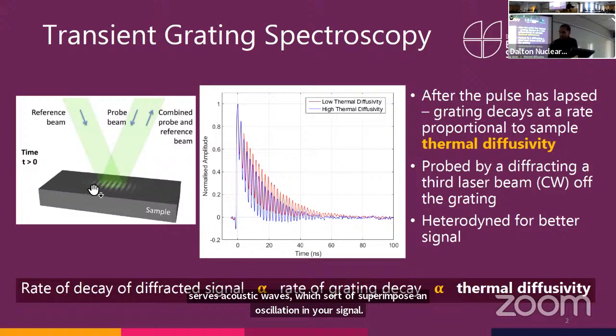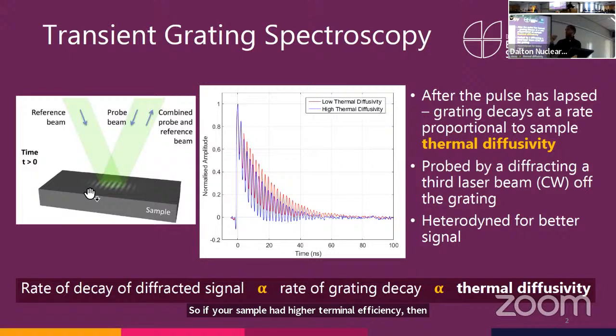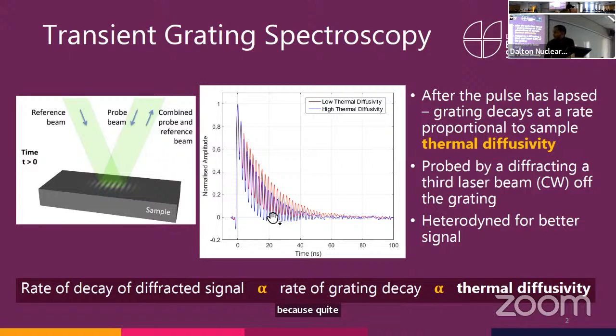So if your sample had higher thermal diffusivity, then once the laser pulse is gone, the heat would flow from the hot regions to the cold regions quite quickly, and then your grating would decay. So we probe the rate of decay of this grating by shining another laser beam on the same spot and looking at the intensity of the diffracted beam. And as we see, in a sample with high thermal diffusivity, the intensity of that diffracted beam decays quite rapidly, slightly faster than a sample with lower thermal diffusivity.